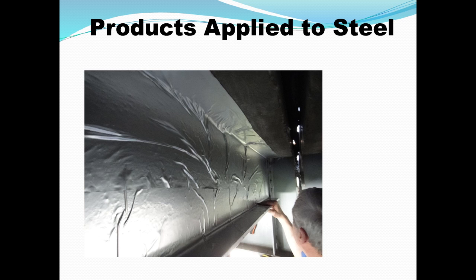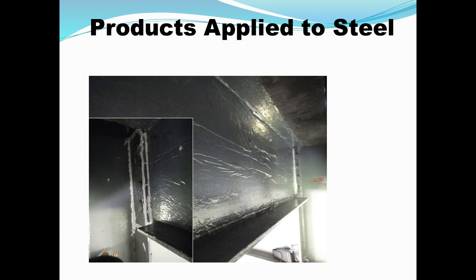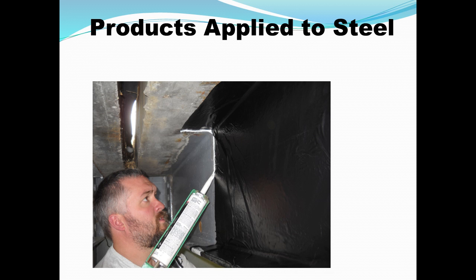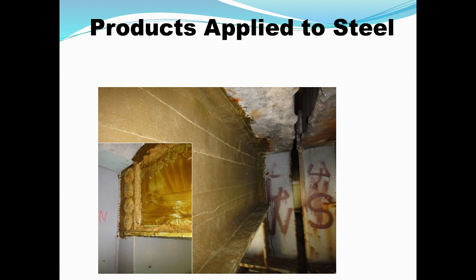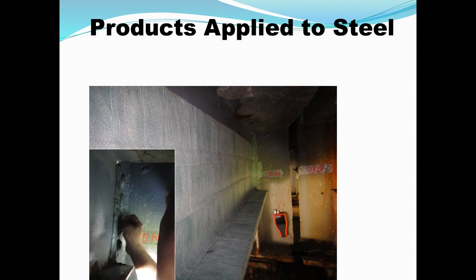And this is one of the sheets where it's only 2 pieces that cover the top flange, the bottom flange, the web, and has enough room to overlap. And on some of these, we sealed these edges with a polyurethane caulk, like this one. And a couple of these tapes use a product that's a petroleum grease with styrofoam pellets that you use to put in these corners or around bolt patterns, because the tape's fairly thick, and we didn't want to leave voids there, so we used that material to sort of round those corners out. And this one did the same thing. This is a different product, but it uses stuff, as you can see in the inset, where we're putting the putty-like stuff in the corners.